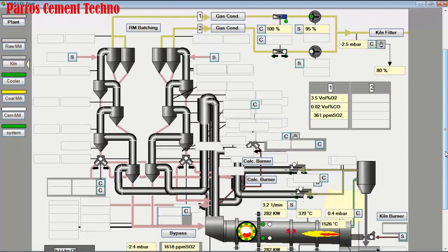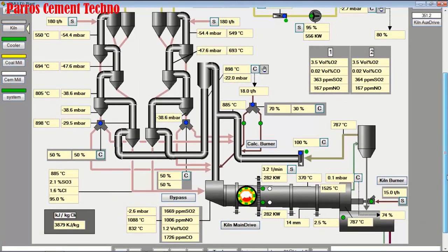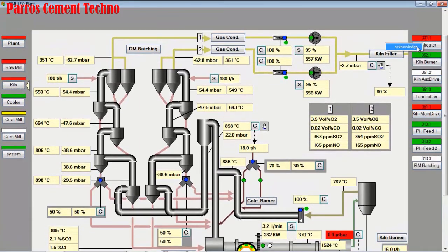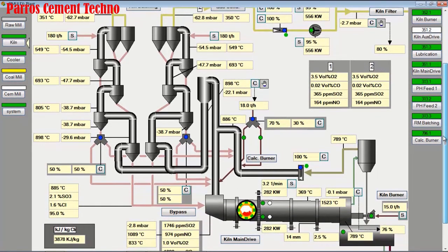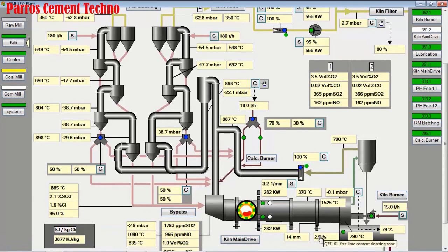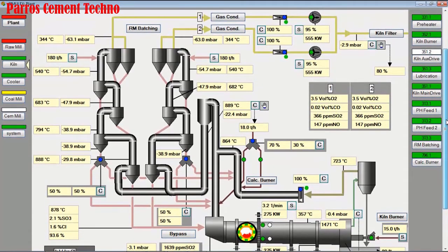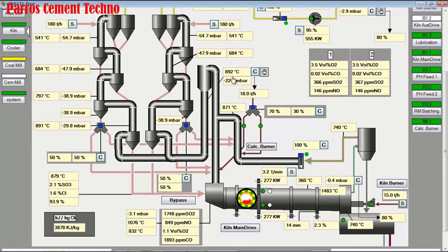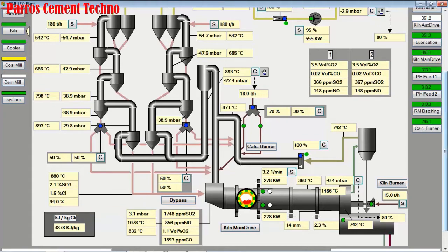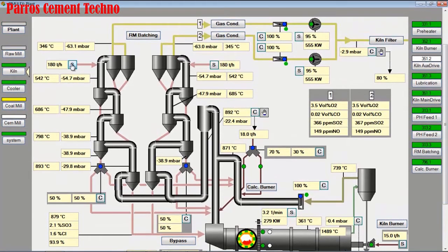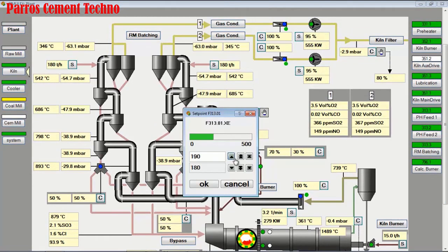Returning to the kiln display monitor, we reset several alarms caused by changes to the cooling system, as the kiln hood draft is close to positive. Decarbonization is at 95%, but free lime is still 2.5%. The temperature in the calciner is still quite high at 890 degrees Celsius and decarbonization is 94%, so we increase the kiln feed again to 190 tons per hour each, for a total kiln feed of 380 tons per hour.